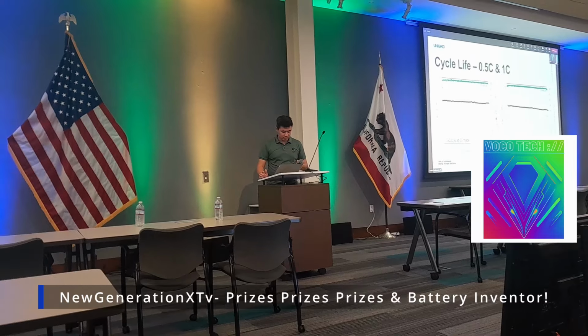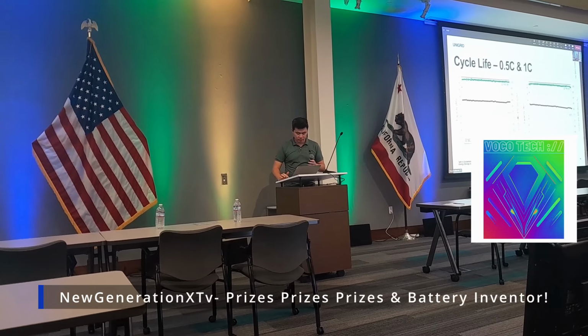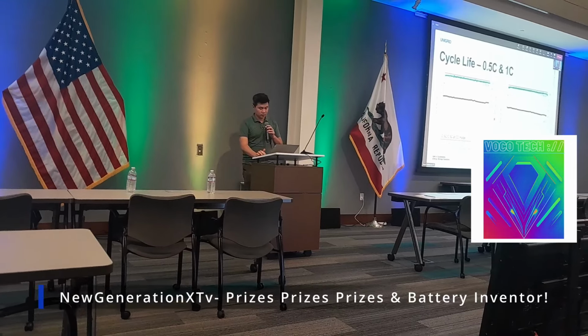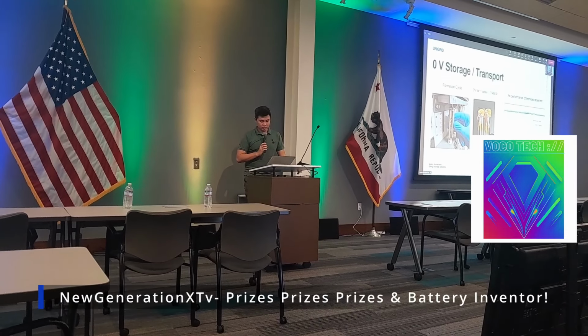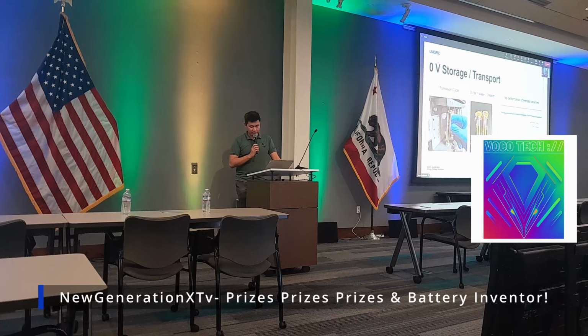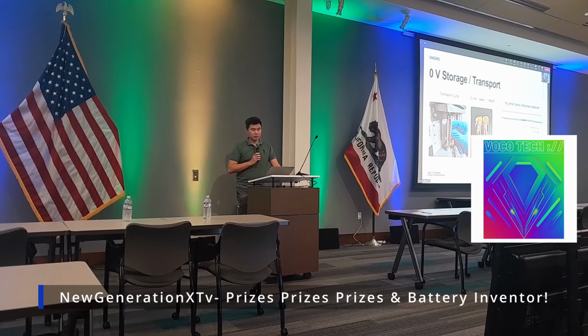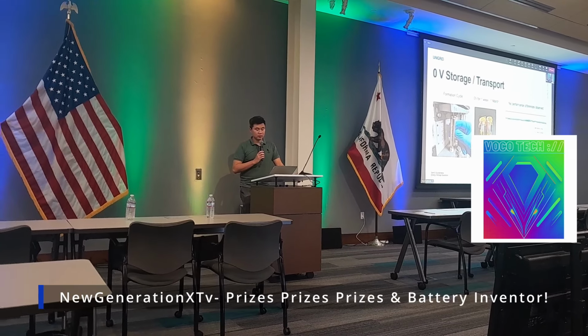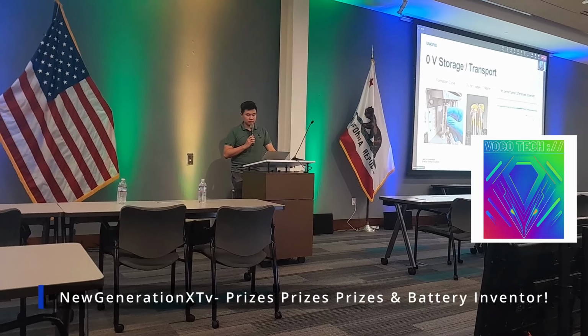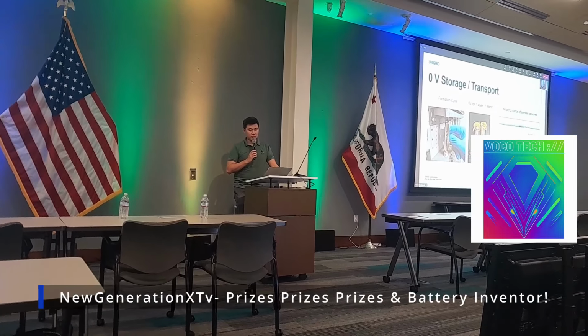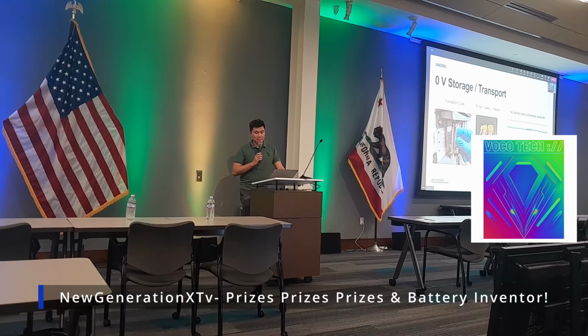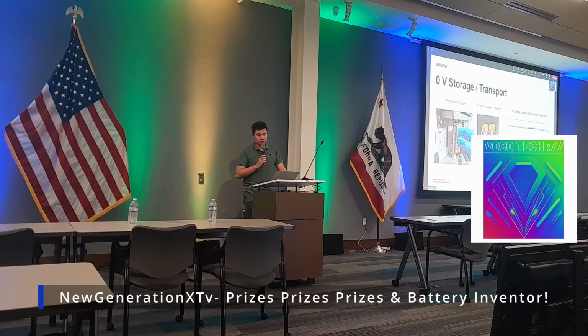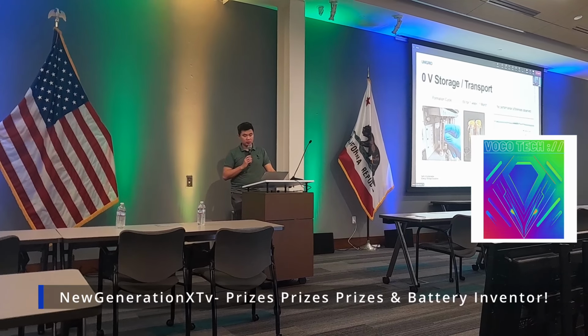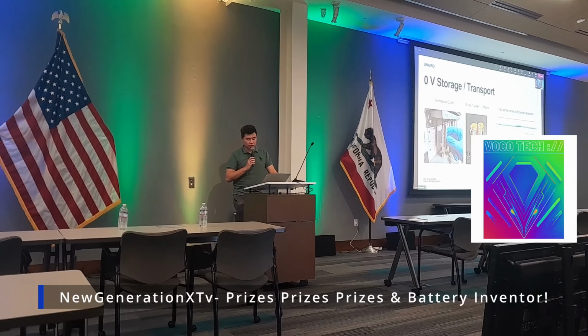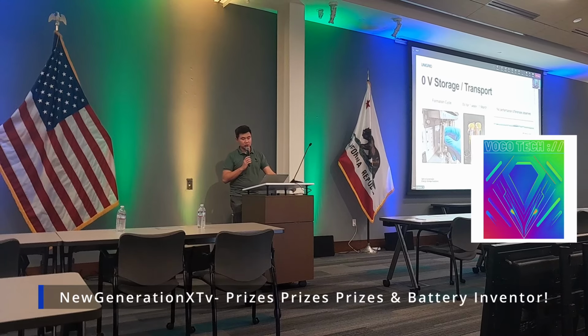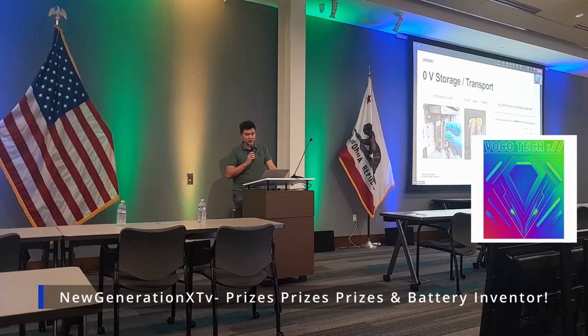Well, actually, it was a slide after the 0 volts. In other words, if there's an unintentional complete depletion, lithium gets very damaged if you go to 0 volts. Correct. And I was very happy to see that you're very resistant to damage at 0 volts. It's just that there wasn't really a large cycle test after that, and that's where the damage shows up on the lithium, is that the lifetime of the battery is greatly reduced if you bring it down to 0 at any time in its life. Yes, I agree. We do have longer ones for this. It's just my engineer didn't plot enough cycles for this.